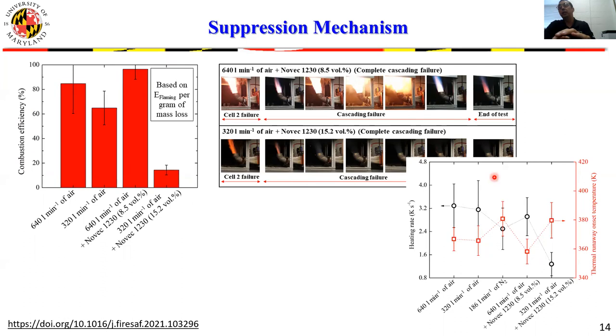And the data that we collected clearly indicated that Novec contributed to the cooling of the cells that were sitting next to the cells that already underwent thermal runaway. And that cooling was generally responsible for that stoppage of the cascading failure.